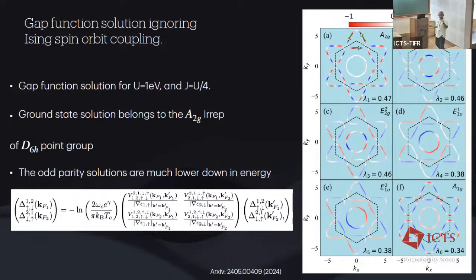I write D6h because for this solution that I'm showing, I'm ignoring the spin-orbit coupling for the moment. So the lattice symmetry is not reduced. Now, again, you can see that this is indeed an even parity solution. So this can be decomposed into even and odd parity because spin-orbit coupling is ignored. And for the even parity solution, the odd parity solutions are far lower in energy. So it is along the lines of an even parity A2g solution with a small gap on the gamma-centered pocket.